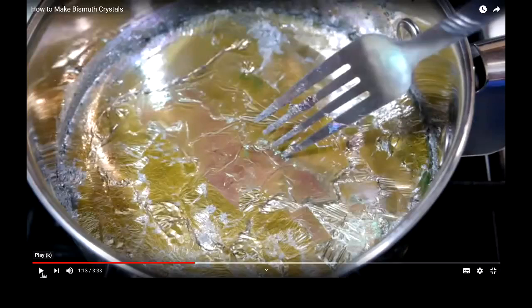What's another one? The last one's just the temperature gradient. Okay? So at the surface we're air cooled, whereas from the hot plate we're heating from the base, and then around the outside of our saucepan. So we've actually got slightly hotter around the edges. Right? So just based on those two things, the inoculation at the surface plus the temperature gradient, we're getting crystals forming on top and growing down into our melt.